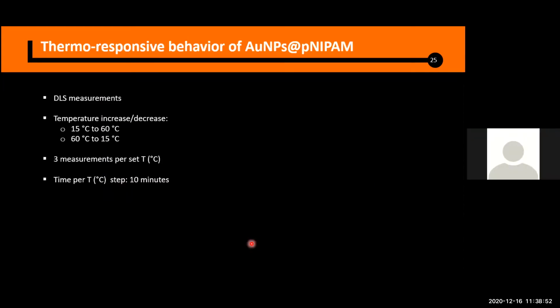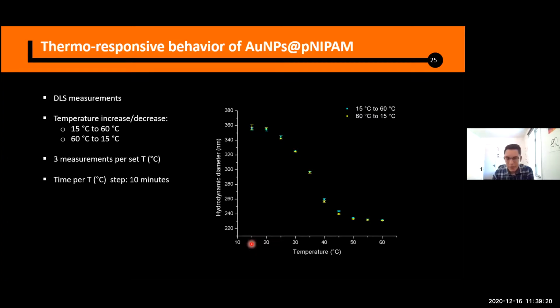So, for example, to study the thermoresponsive behavior of this material, I performed these DLS measurements, but measuring the hydrodynamic diameter at different temperatures. I did two different tests, from 15 to 60 degrees Celsius and from 60 to 15, to see the reversibility behavior of the hybrid material. And this is the typical particle size transition curve when increasing the temperature.